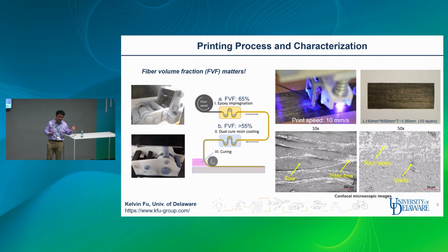But if you look at other types of towpreg or 3D printing companies, they claim they can achieve high fiber volume fraction. Normally their fiber volume fraction only reaches like 20 or 30 percent by volume. Okay, it's pretty low. So that shows our printing process, and here's the cross section. We can see those dry fibers. They are fully impregnated by the epoxy, so they are very densified.